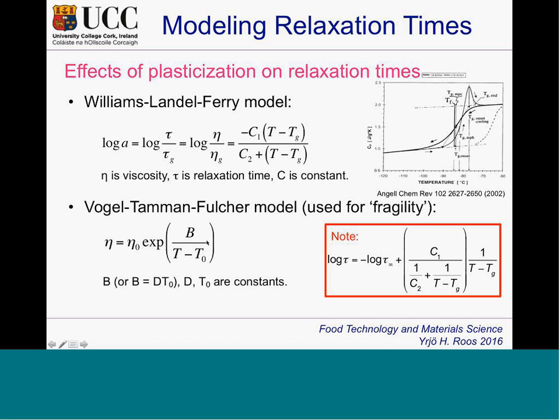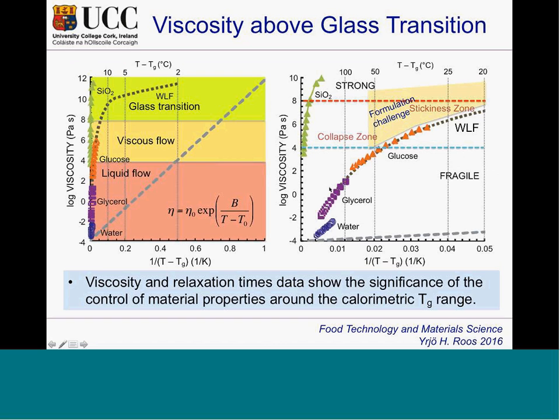And if we plot data accordingly, we could have silica glass here, and then we could have WLF data for a number of materials. They are here: glucose, water. They go quite clear. But we have a zone that is a critical zone above the glass transition for a number of food solids. Then you look at the WLF relationship.